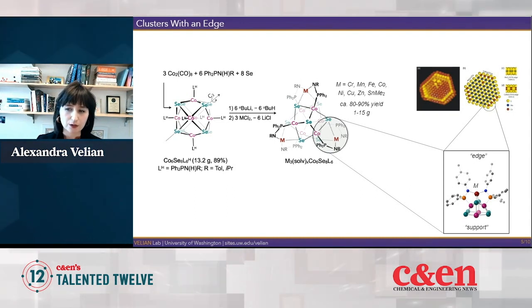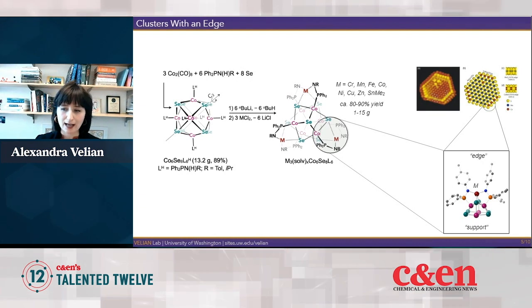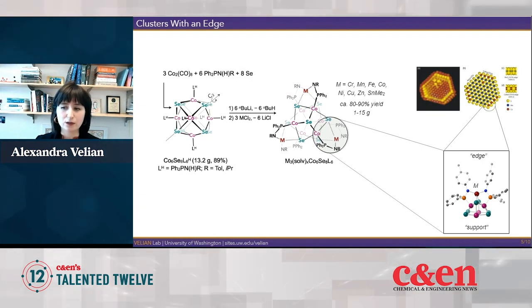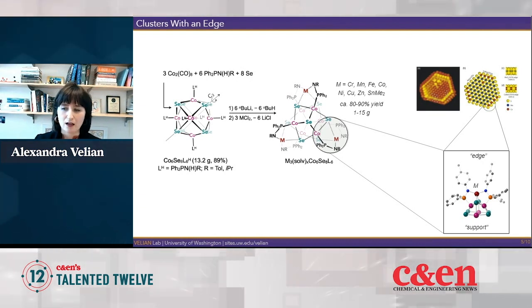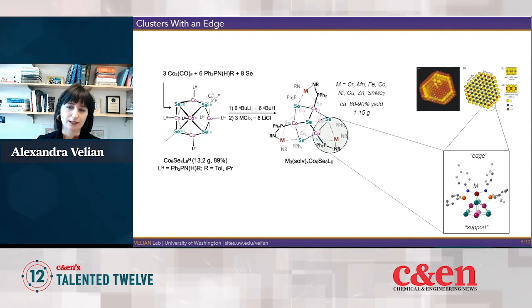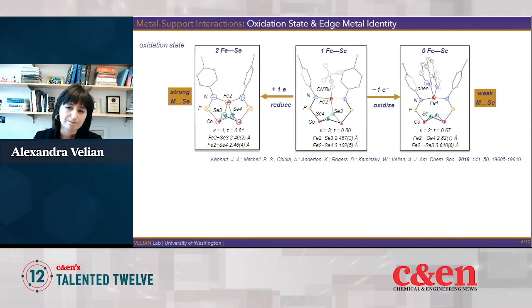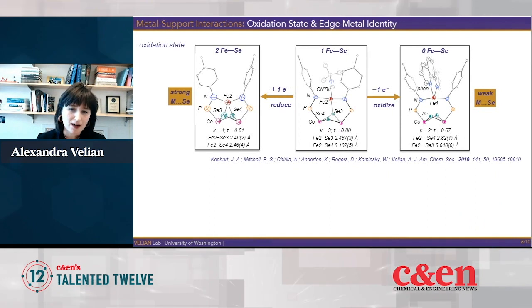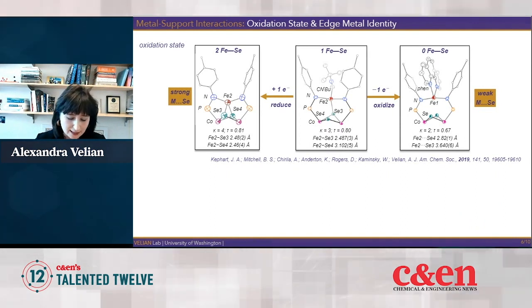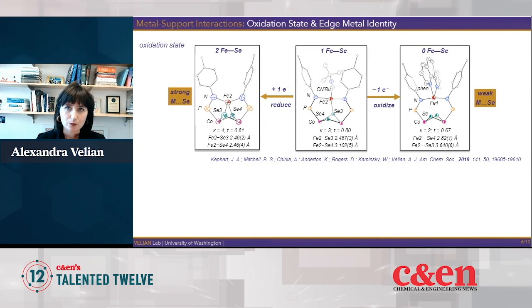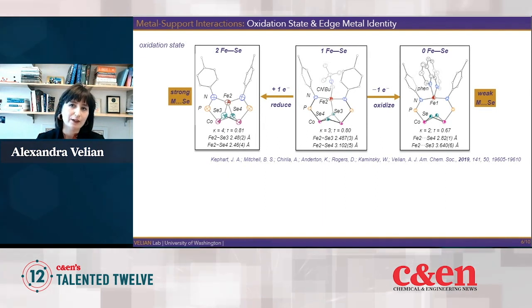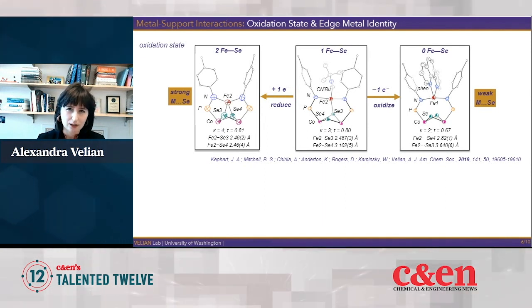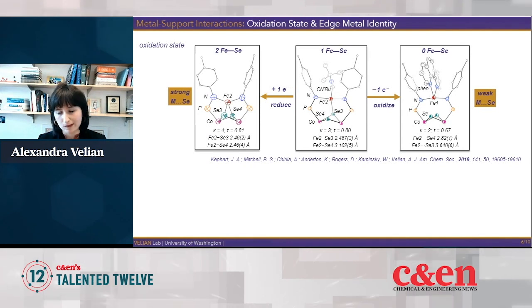So I'm highlighting on the edge, on the right side, the edge itself, because this is really central to the reactivity of the clusters. And so let's take a closer look at it. The edges are emulating these active sites that I mentioned previously, which are known to have, oftentimes, a low coordination environment at the metal.